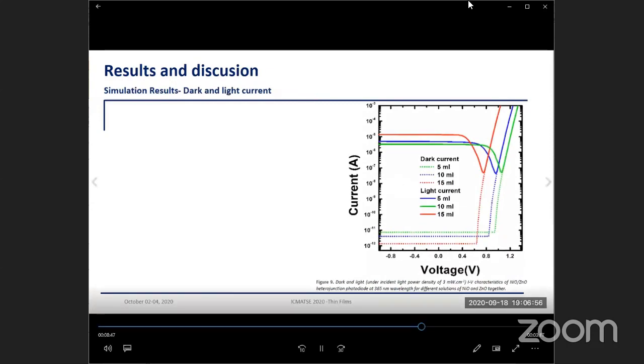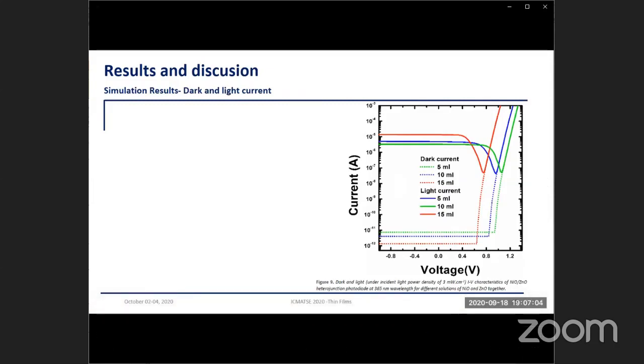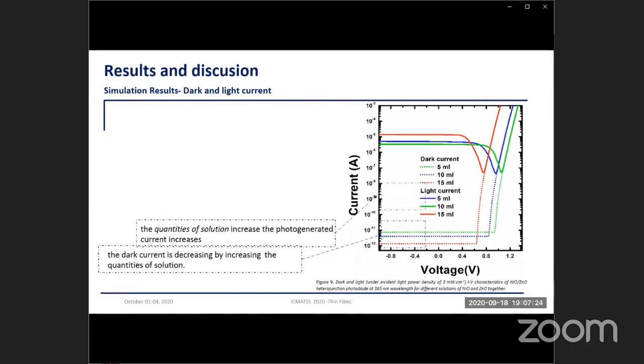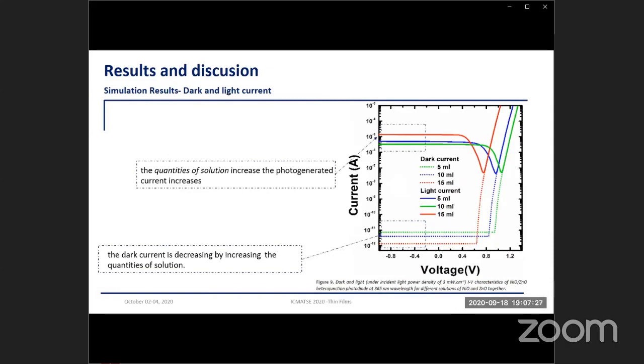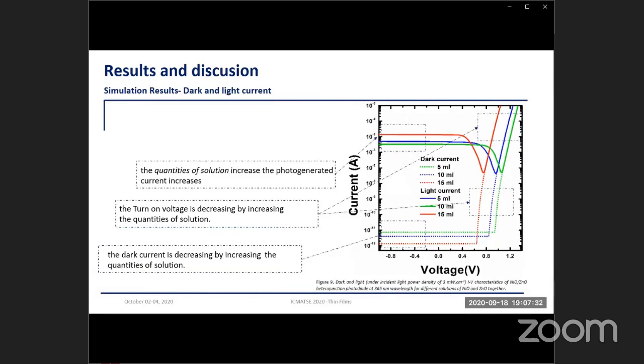As we see in the following graph, the variation of the current voltage characteristics under dark and illumination as a function of the quantities of solution of the two materials together, nickel oxide and zinc oxide. The first observation is the dark current is decreasing by increasing the quantity of solution. In contrast, the photocurrent increased by increasing the quantity of solution. And we can see that the threshold voltage is decreasing.